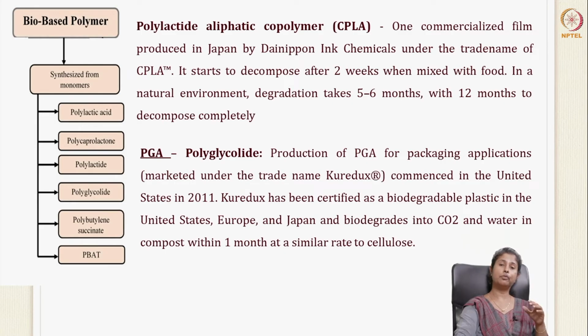A third type of monomer that you can add is the polylactide aliphatic copolymer, CPLA. One commercialized film produced in Japan under the trade name of CPLA starts to decompose after 2 weeks when it is mixed with food. In a natural environment, degradation can take place in 5 to 6 months. Within 12 months, it can even be decomposed completely. So this is another important monomer that is to be looked at in future.